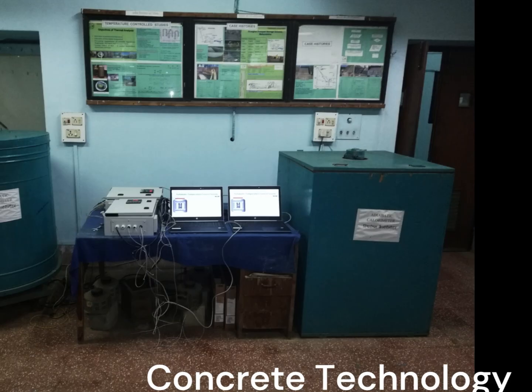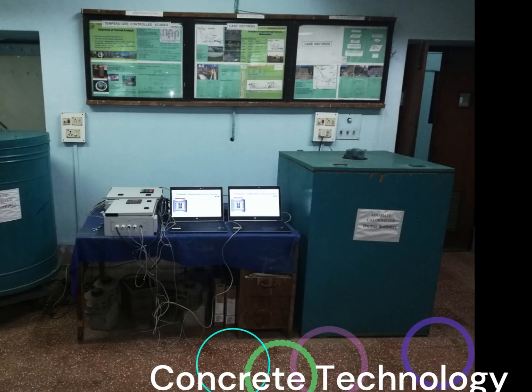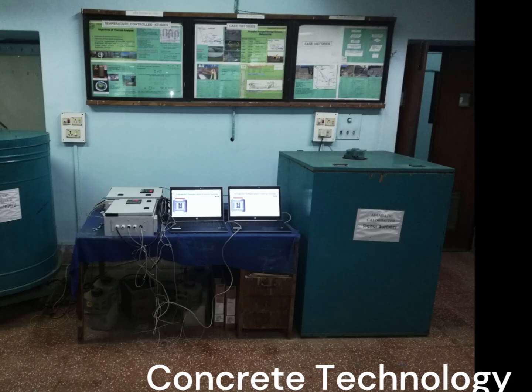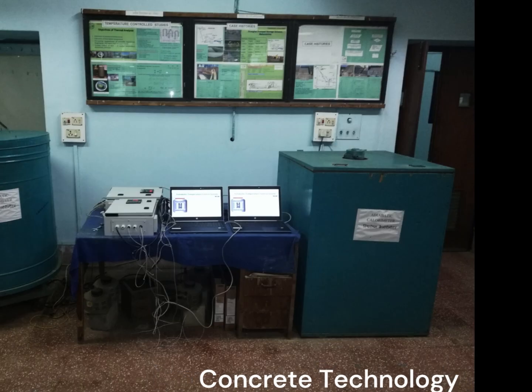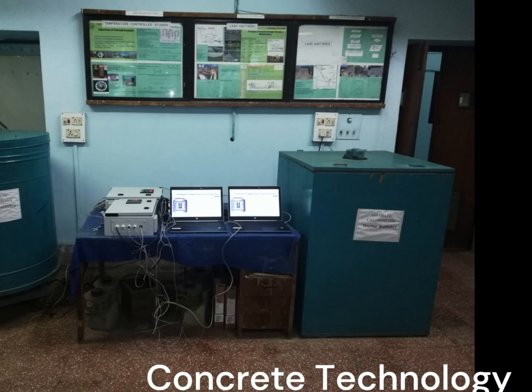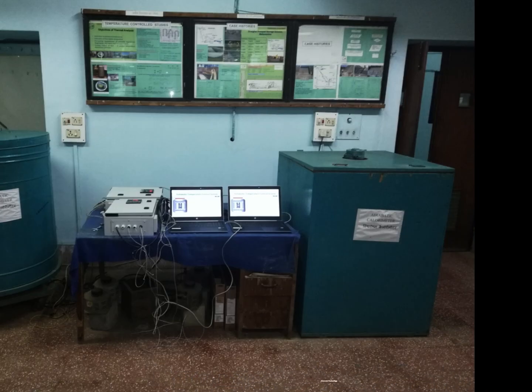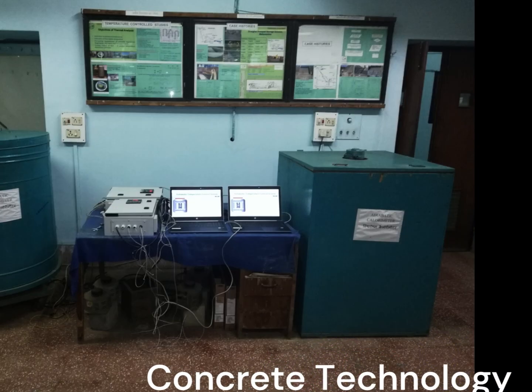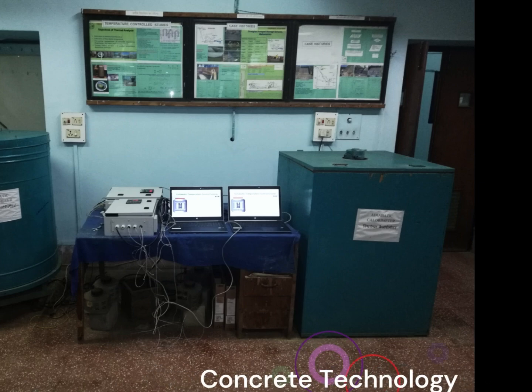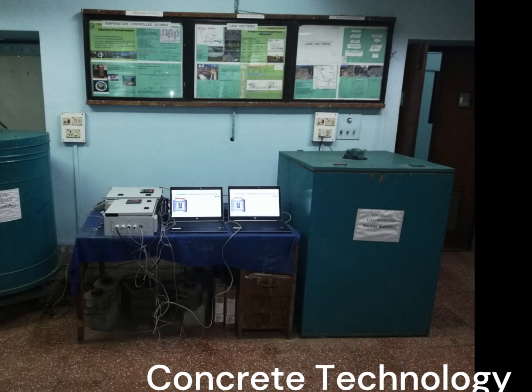The temperature of the concrete mix and the chamber are measured by highly sensitive platinum resistance temperature detector. To achieve the adiabatic condition, the temperature of the chamber is so adjusted that difference between the specimen temperature and chamber temperature at any time does not exceed 0.5 °C. Under adiabatic conditions, the temperature rise in the concrete mix sample is monitored and recorded for a period of 7 days. The rise in temperature of concrete is plotted against time in hours.